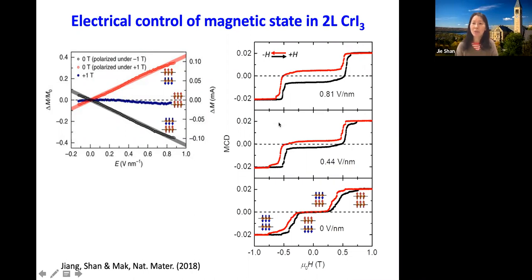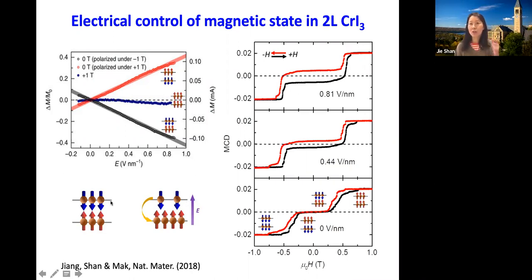The microscopic mechanism of this effect is still under study, and this could be an explanation: when you apply electrical fields, the two layers are at different potential, and you can induce a charge transfer from one layer to another. Because of the strong interlayer magnetic interaction, the spin transferred to that layer will have to line up with the rest. Then in this situation, the net magnetization will be up. So that's how we can get non-zero magnetization when you apply field. This also gives us a hint that if you can introduce doping into the system, perhaps you can do this more efficiently. And that's what we tried in the next experiment.